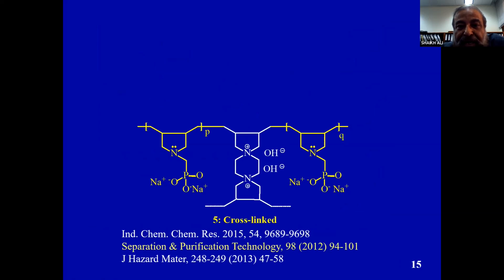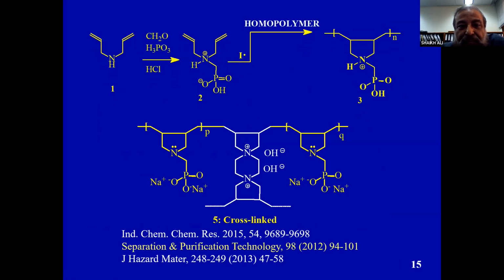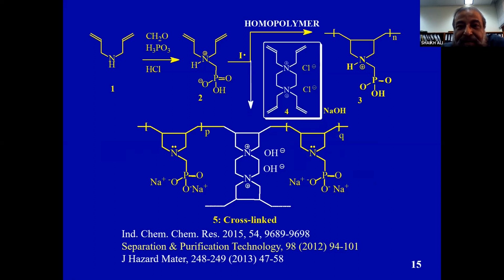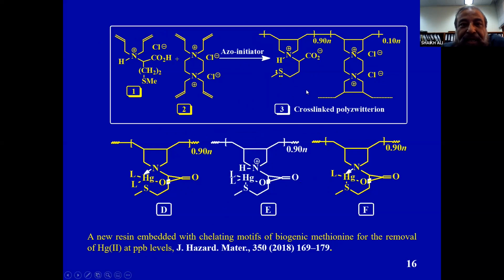Now, I want to take you to another cross-linked polymer. This is here, this is the monomer, and this is the polymer. This is the cross-linker, these white rings, this cross-linker. So it becomes cross-linked. Now I want to take you, using this cross-linker again, number one is derived from the amino acid methionine. And that gives us this cross-linked polymer, which has a nitrogen H+, and you have a sulfide, CO2 minus. And they are, again, very successful in removing mercury at ppb levels.